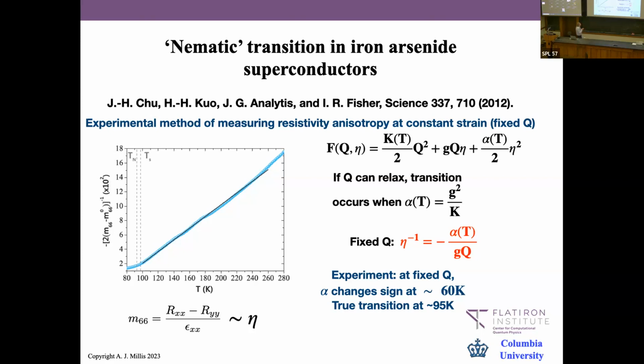So this is a plot of their results, and what you're supposed to see is that the inverse of the resistivity anisotropy, that is the inverse of our electronic order parameter, has an approximately linear temperature dependence. In what I think is a spectacularly bad piece of public relations, they don't extend the plot down to 0, but you can easily see that this would cross 0 about here at 60 Kelvin. So this is a statement that in this material, the transition is intrinsically electronic, just boosted up from the say 75 Kelvin you'd get by extrapolating this line, to 95 Kelvin by the cross-coupling, right?